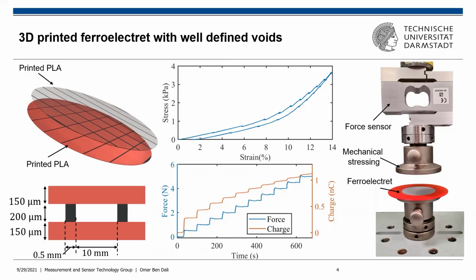When measuring the mechanical properties of the ferroelectrets, we found out that using the ridges also reduces the Young's modulus of the structure and makes it more flexible, and thus large deformation for a relatively small stress can be reached, as you can see here. Furthermore, until a strain of 6% is reached, the ferroelectret sensor shows a linear behavior. However, the piezoelectric response of the ferroelectret is not linear, which should be taken into consideration when designing a sensor.